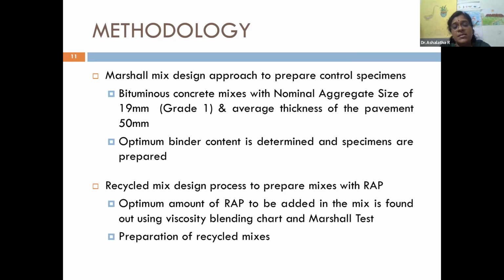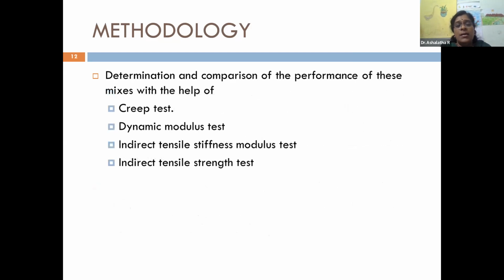And the recycled mix design process to prepare the mix with RAP. In that case, we found out what is the optimum amount of the RAP we have to add in the mix. This was the one which we found in the literature at that time. It was found out using the viscosity blending chart, and the recycled mixes were prepared. And we also determined and compared the performance of these mixes. We conducted creep tests, dynamic modulus tests, indirect tensile stiffness modulus tests, indirect tensile strength tests, etc.